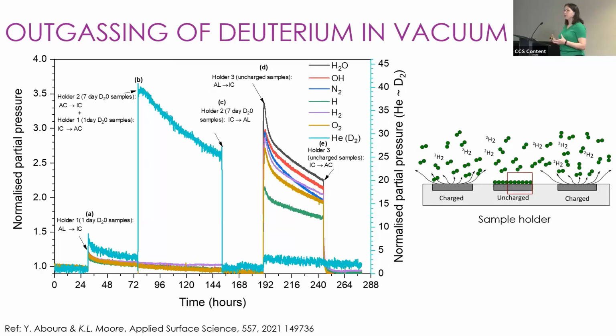So this really proved to us that the deuterium is outgassing from our sample while we've got it in the NanoSIMS, so we have to work fairly quickly to do these experiments. Just to show that in a more visual way, we've got deuterium coming out of our charged sample. And the implication of this as well is that if we have an uncharged sample in the same sample holder, some of that deuterium is going to deposit on that surface, and we can never measure the natural isotope ratio as we would expect from an uncharged sample. So any areas of our sample that do not contain any deuterium, we will always detect some deuterium from there. So it has implications on our detection limit.